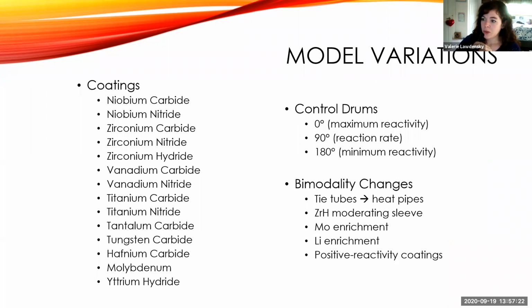Yes. These are all the different coatings we looked at. It was many. We tried to do carbides, nitrides, and hydrides. The carbides are common, they have a lot of information, and they fit well with graphite. The nitrides and hydrides, though, have this benefit of being a little friendlier with hydrogen, but even more importantly, are moderators. So we would have a better sustained nuclear reaction, especially in the case of adding in heat pipes. When we'd be taking out a huge moderator element, we need to replace something somewhere.